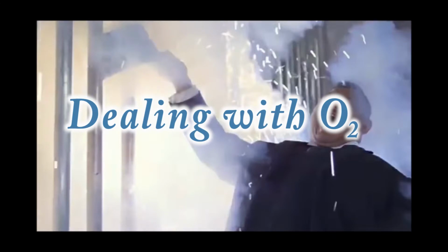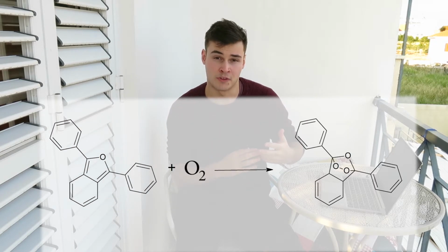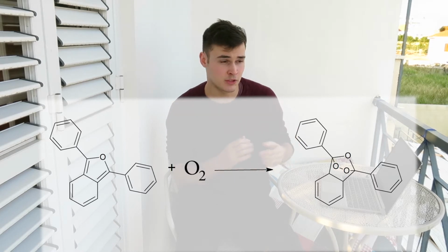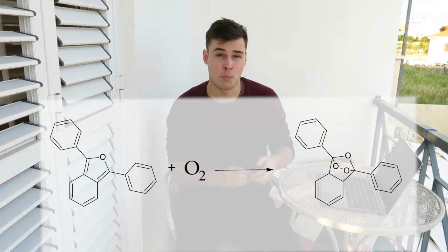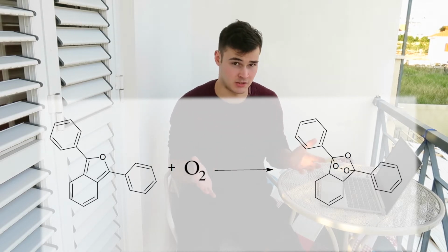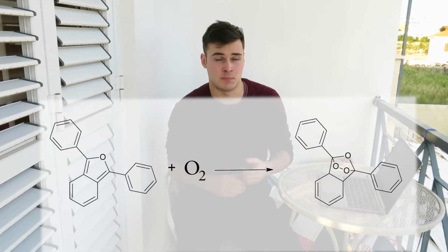However, reducing oxygen can be done in a multitude of ways. Often, oxygen scavengers are employed. These molecules, like diphenyl isobenzofuran, react preferentially with oxygen over the radical. But this means enough scavenger has to be present to absorb all of the oxygen that will diffuse in through the entire polymerization process. On top of that, a quenching time must be allowed for before initiation may proceed to reduce the oxygen levels.